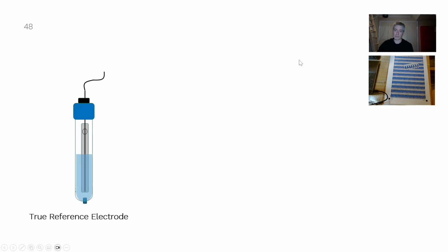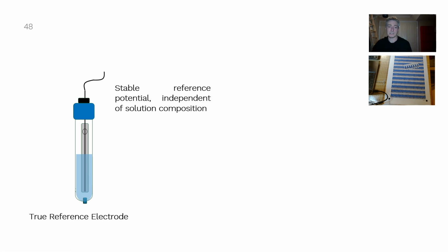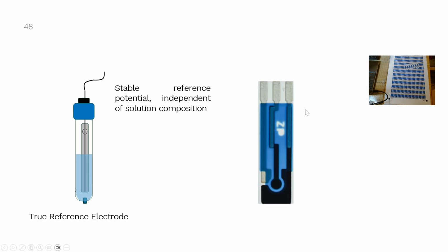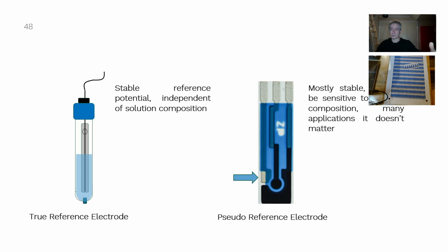With a true reference electrode, you've got everything locked behind this porous frit. You would run it at a known chloride concentration, and therefore you should have a stable reference potential independent of the solution composition. But if you took a screen-printed electrode, which would be a pseudo reference electrode, then it would be mostly stable, but can be sensitive to the chloride concentration, and that's what I've demonstrated so far in this video. You can go from 1 molar, where the peak potential would be 200 millivolts, but if you went to 0.1 molar chloride concentration, it would suddenly shift to 141 millivolts. There's a shift of 59 millivolts, reflecting the 10x dilution.